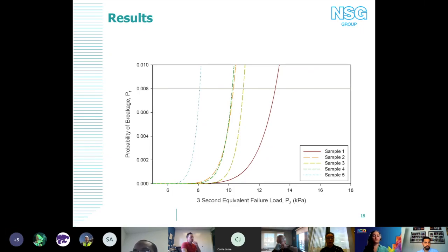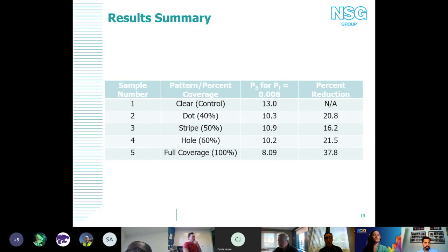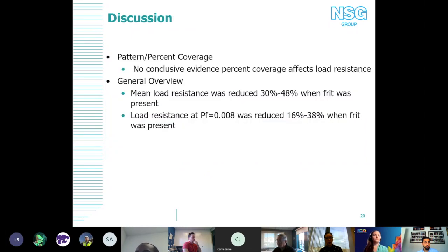And here's just the probability of failure of 8 in 1,000, so you can see what that looks like with regard to E1300 design. What we saw was a load resistance reduction ranging anywhere from 16 to 38%. It's interesting to note that samples 2 and 4 are fairly close in their percent reduction, and their patterns were exactly the inverse of each other. So it may have something to do with the layout of the pattern versus the stripes, which followed a different layout. I don't really have an answer for that necessarily, but essentially we're still getting a fairly significant reduction.